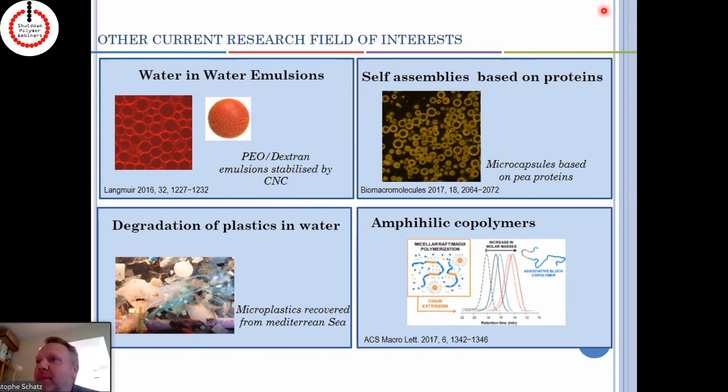The first question for you: can you blend polymer that is not tempered with tempered polymer in the same way as polymer with different amounts of acrylic acid? Okay. So I told you that you have to obey some rules in terms of blending. We have tried to blend frozen self-assembly with non-frozen one, and it was not possible to obtain hybrid self-assemblies.